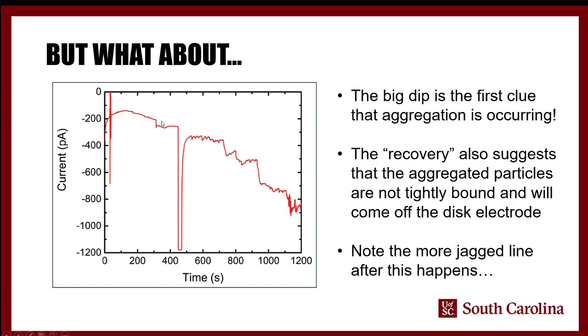In the course of some of the experiments, and actually I think it happened in every single one at some point, it would be going along showing relatively small steps, and then all of a sudden you would see a step that was a nanoamp or larger. The reason it goes down here and flattens out is that it maxed out the current range of the potentiostat, so it could not measure a current value higher than this. But what we see is that it also comes way back.